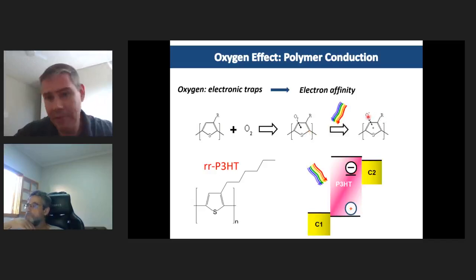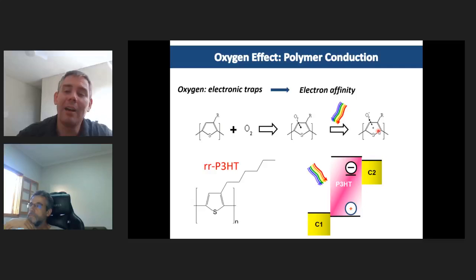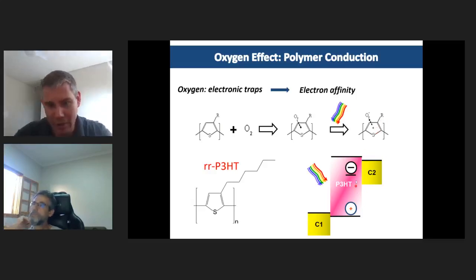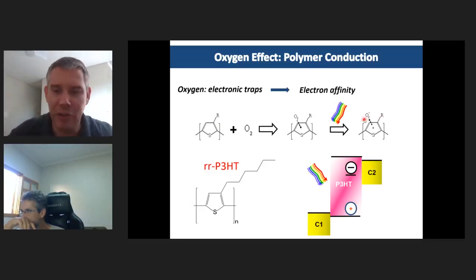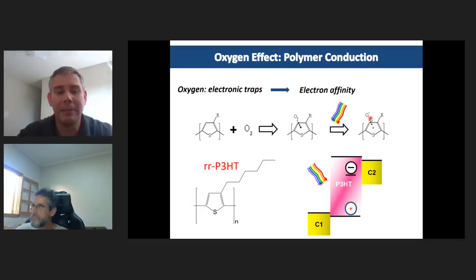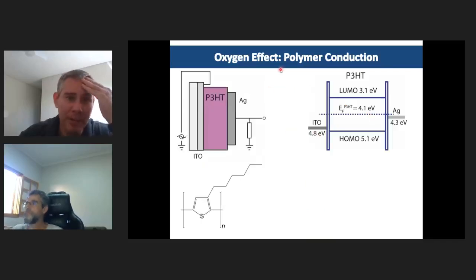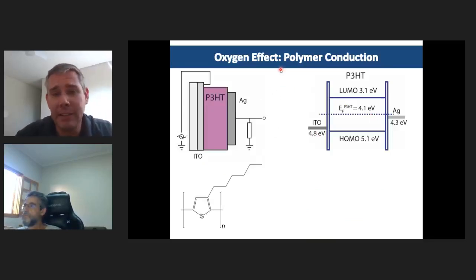And therefore, because of the electron affinity, the oxygen traps or steals an electron from the conjugated molecule and p-dopes the molecule, because when you remove an electron from the polymer, which before was neutral, you leave a hole behind, the vacancy of that electron. And therefore, there are a lot of problems with this charge transfer electron trap states. This is the big name that the community calls it. And it's very difficult to study this phenomenon in order to try to avoid it, right?